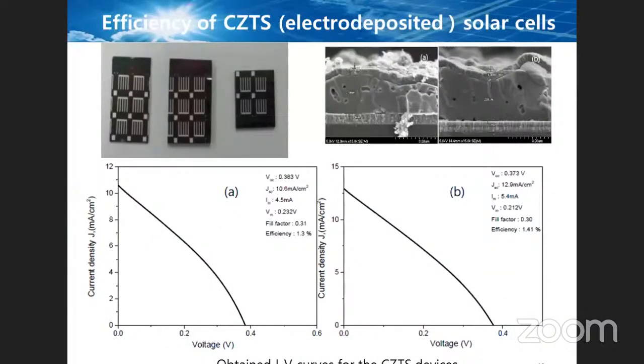Next one. Also, we made some solid state device of the CZTS. Okay, see this. What is the structure of the CZTS solar cell here? See, this is our moly. Glass is here. After that, moly is deposited on the glass. And after that there is the CZTS precursor here, and then there is a very small CdS layer, 70 nanometer, that is deposited by chemical bath deposition, and thereafter there are zinc oxide nanorods that are deposited by the evaporation method, and after that there is some contact.